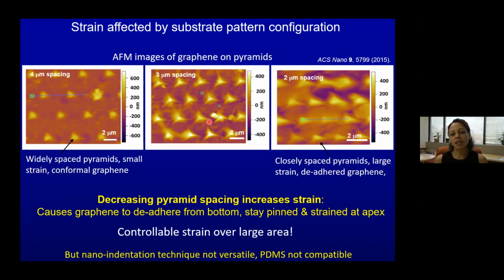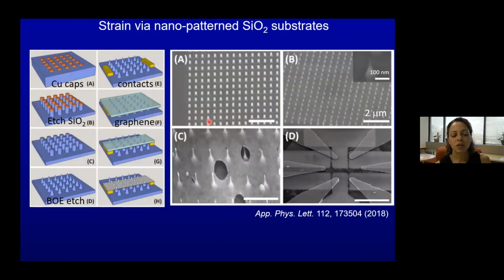Now, that's good, but it turns out that for one, the nano indentation technique is very time consuming. It's not that versatile. And the PDMS wasn't compatible with the electronic devices that we want to make. It's hard to measure transport on a piece of rubber. And we also wanted even smaller features. Like I said, we're aiming for things that are of the scale of 20 to 100 nanometers. Okay, so after showing that we could indeed induce strain, we tried to move to something that was more device compatible and smaller. Okay, so that means that we ended up doing something lithographically.